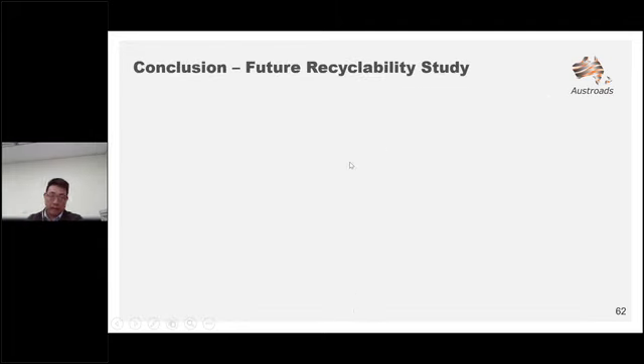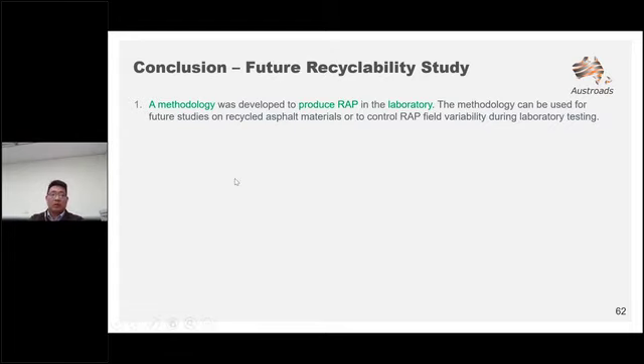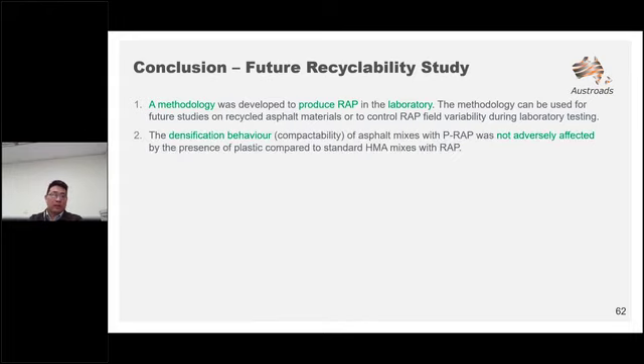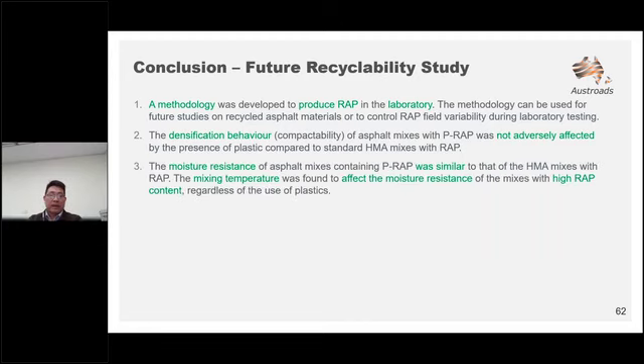So overall, it is concluded that in this study, a methodology was developed to produce RAP in the laboratory condition. And the methodology can be used for future studies on recycled asphalt materials or to control RAP field variability during lab testing. The densification behavior or the compactability of asphalt mixes with PRAP was found not adversely affected by the presence of plastic compared to a standard hot mix with RAP. And the moisture resistance of asphalt mixes containing PRAP was found to be similar to that of the hot mix with RAP. We also found that the mixing temperature was crucial, and it affected the moisture resistance of asphalt mixes with high RAP content, regardless of the use of plastic.